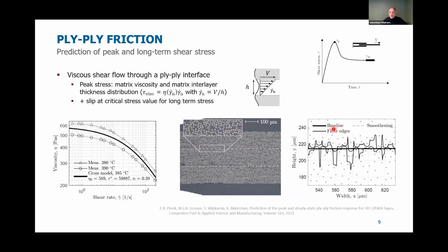We have our viscosity, so we are able to describe the stress growth and the stress. We can describe the peak of the shear stress. Thing is, after the stress peak, there's a decrease to this long-term shear stress. But that can only happen when there is slip happening at the walls. So the peak stress is modeled with a no-slip, so a stick condition. Here there must be a certain slip, and for this, when the shear stress is higher than a certain critical stress, slip occurs, then we have the drop. And for this critical stress, we take the value of the plateau that we saw earlier.